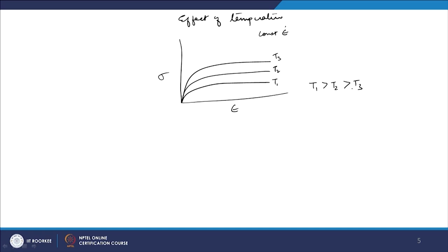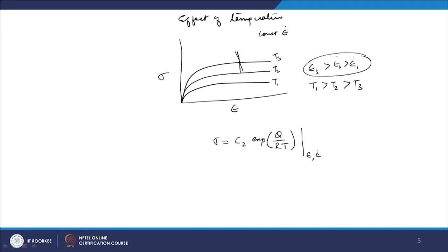So, it is exactly opposite of what we saw in the case of strain rate. In the strain rate, I said epsilon dot 3 will be more than epsilon dot 2 and then epsilon dot 1. That was the case there, but here for increase in flow stress, the condition will be like this. And again, we can define this behavior using a relationship between stress and temperature, which will be something like sigma equals C2 exponential Q by RT, at constant strain and strain rate. Again I can take, at a particular strain rate and strain, different temperatures: at T1, sigma 1 is the flow stress, T2 sigma 2, T3 sigma 3, and so on. You can see that temperature is in the denominator.